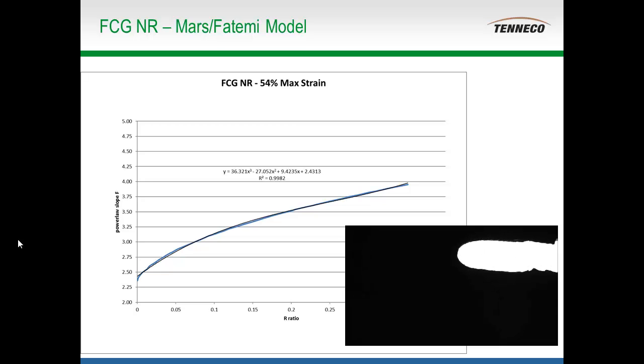So this is basically to perform on strain crystallizing materials. This measures the effect of the strain crystallization on being able to arrest the crack growth rate. So basically what I'm showing here, typically this test is run at several max strain levels, and once you have achieved a steady state crack growth, you start ramping up your minimum strain, and you basically get what's known as the R ratio, or just the ratio between max and min strain.